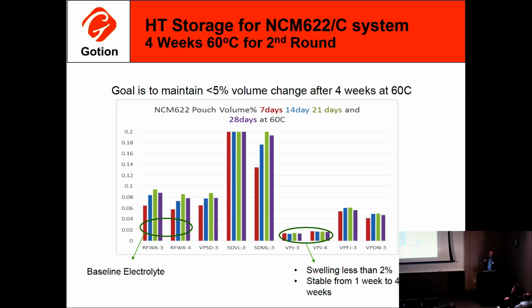The first bar is 1 week, 2 weeks, 3 weeks, 4 weeks, and you can see it goes up for the standard electrolyte here. With some technology we've developed, we got less than 2% swelling. And this is in a pouch cell, not in the standard prismatic production cells. So you can really see a difference.